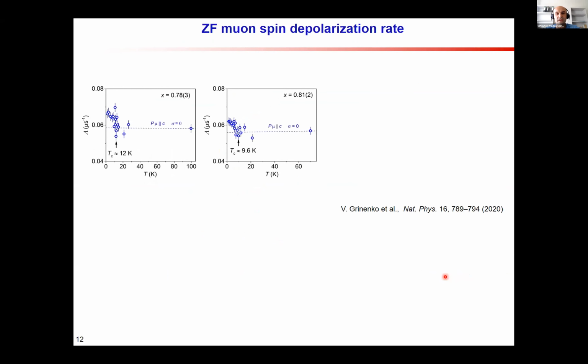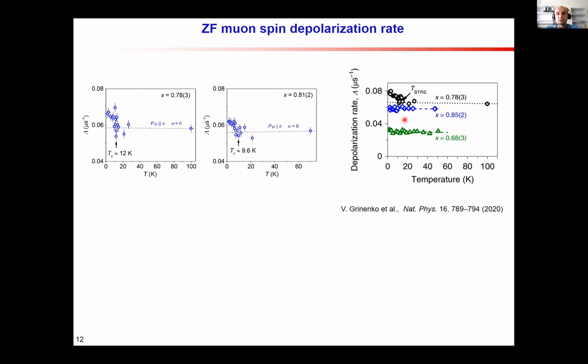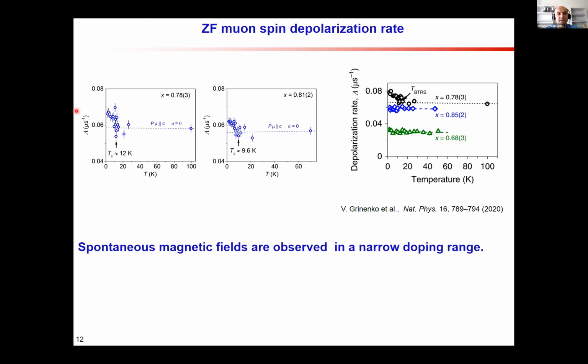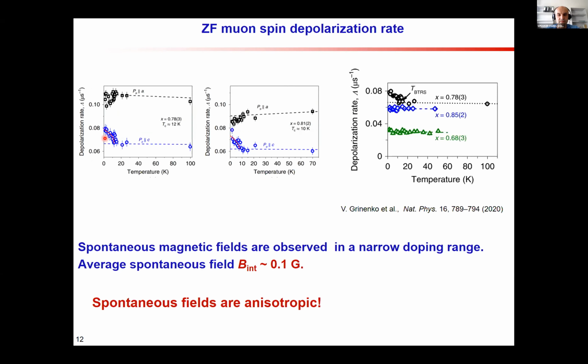So now our central result. The central result is shown here. What we see here is that the relaxation rate is indeed enhanced below the superconducting transition for two doping levels. For the other two doping levels, slightly above or slightly below, we didn't observe such an enhancement. So this enhancement we relate with the appearance of spontaneous magnetic fields in a very narrow doping range. And the size of these fields is on the order of a fraction of a Gauss or Ørsted, similar to other superconductors with broken time reversal symmetry.